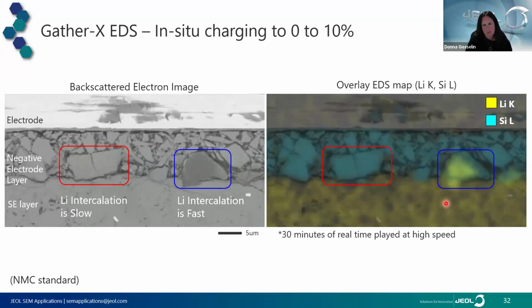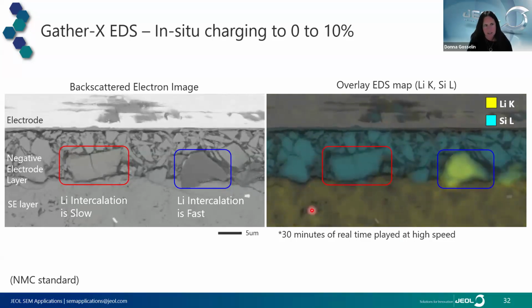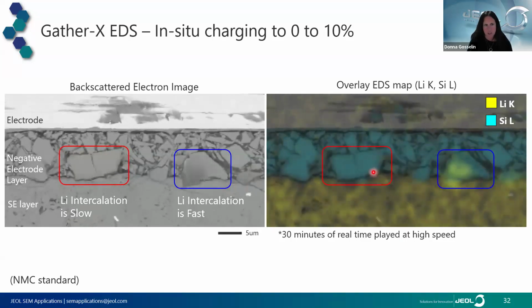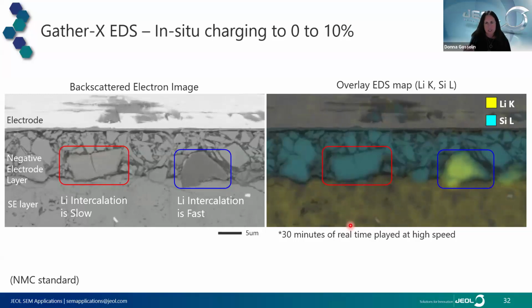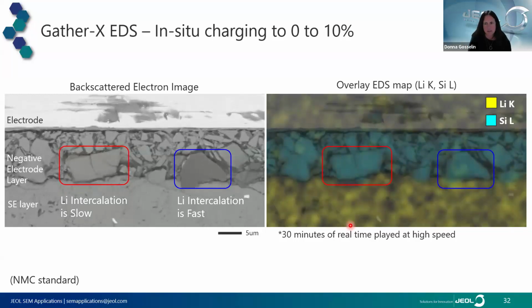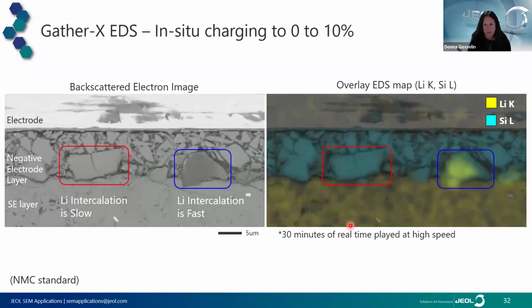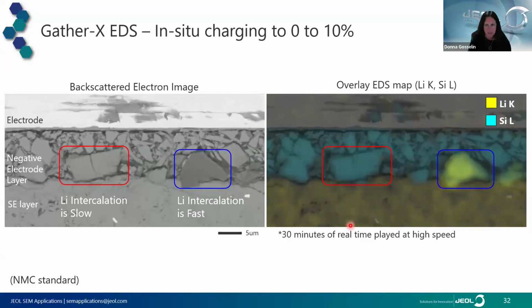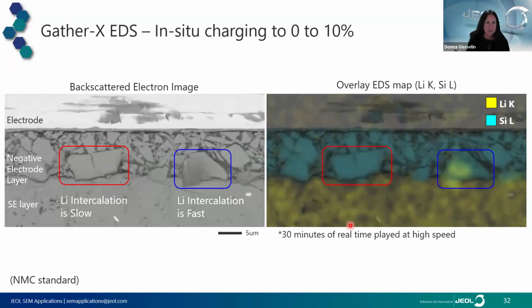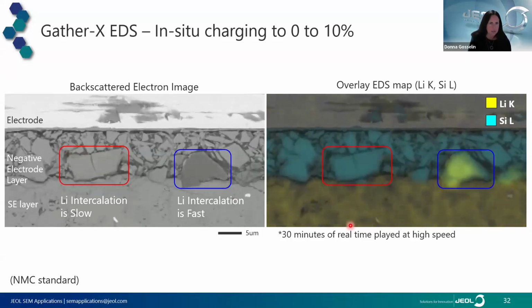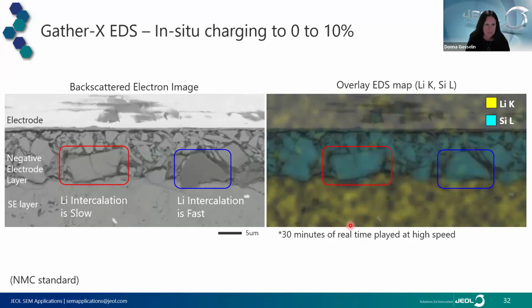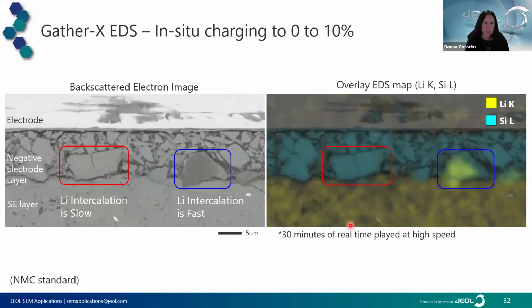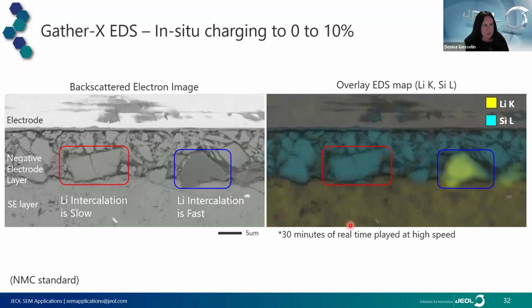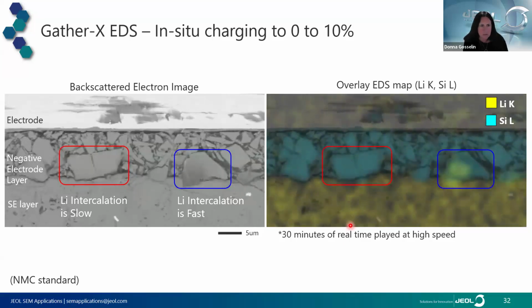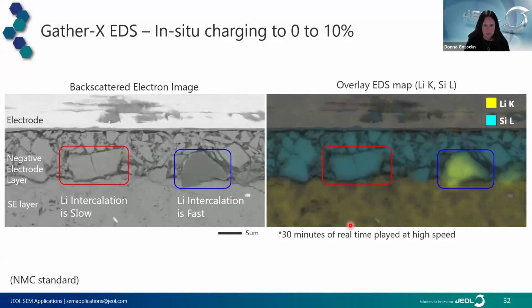Next, I want to focus on these silicon particles on the left-hand side that didn't have much change. We're going to do some further experiments in this charging and discharging cycle. So we're going to basically charge it further and not only look at what the EDS data looks like, but also target it for this soft X-ray emission spectrometer to see if we can get some insights on the chemical state.